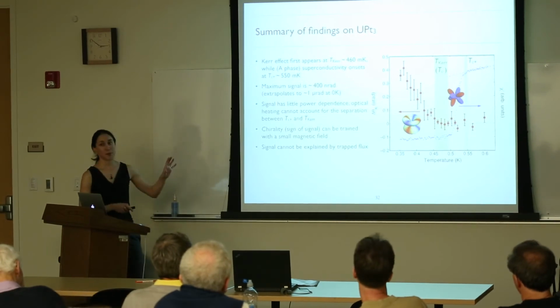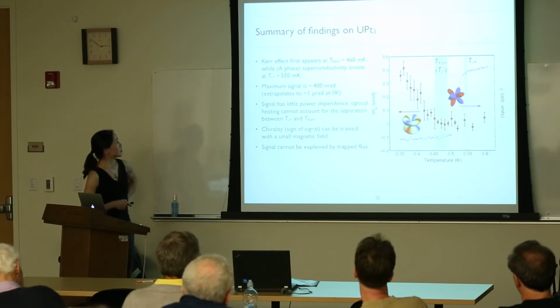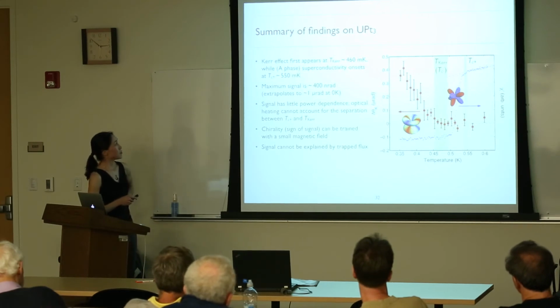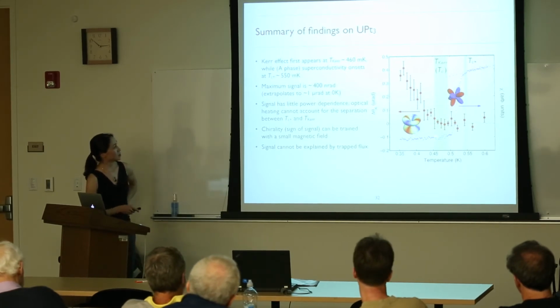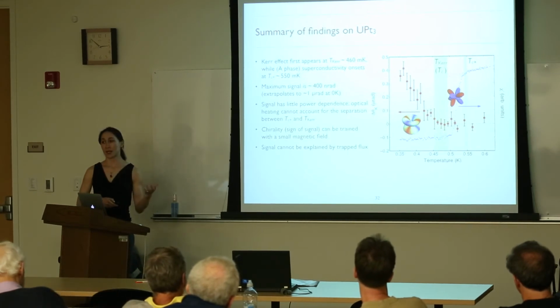All right, so that brings me to the end of our first series of experiments. Let me just wrap up what I've tried to go through here. The first thing, of course, is that we have a Kerr effect that appears below about 460 millikelvin, which is well separated from the A phase superconducting transition at around 550 millikelvin. The maximum signal is quite small, about 400 nanoradians, but it's within the order of magnitude estimate that we can do for this sort of material.